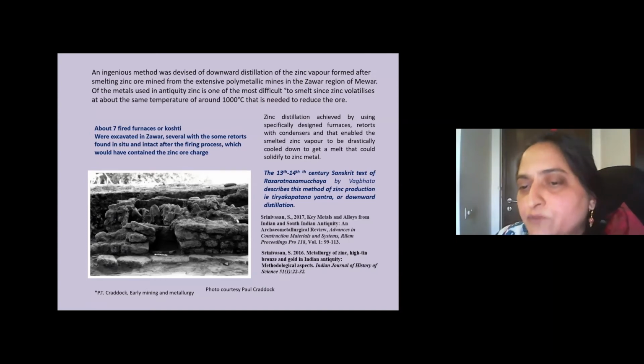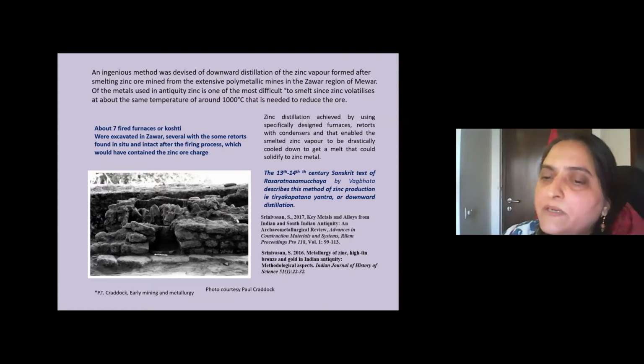For instance, the 13th, 14th century Sanskrit text, which has also been talked about, the Rasaratna Samuchaya by Vagbhatta, describes this method of zinc production as Tiryak Patana Yantra, or the downward distillation. So basically, if you look at the schematic, you get an idea, but you can see here that there's 2 chambers, the top chamber where the retorts were actually fired, and the bottom chambers, and there is a huge thick perforated terracotta layer in between, through which the condenser passes, so that there's a drastic cooling from this top chamber into the bottom chamber.